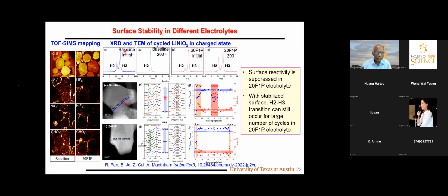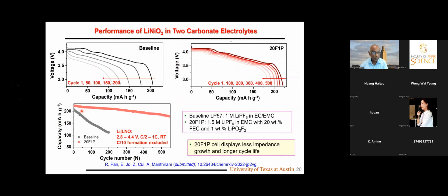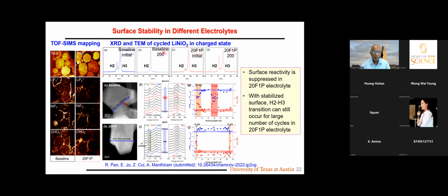In the case of LP57, initially you see H2-H3 phase transformation, but the capacity is falling off like crazy. So when you keep on cycling, after maybe 100 cycles or 50 cycles, you do not go through the H2-H3 phase transformation. You don't see any H3 phases forming. So that's why we don't see much secondary particle cracking.